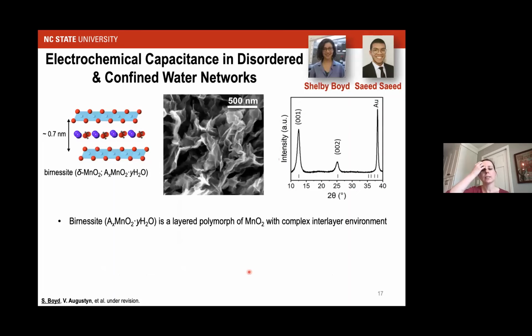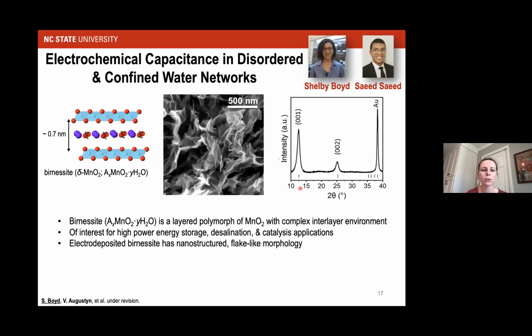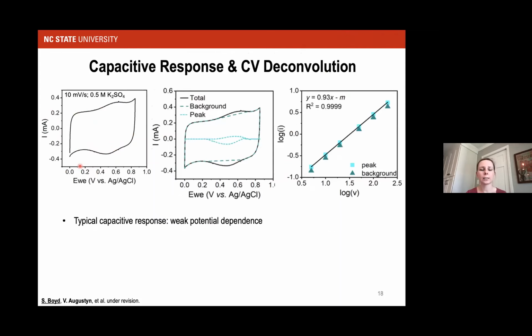To look into this in more detail, we started to work with birnessite itself, that is, birnessite that was synthesized directly. This is the structure of birnessite, very similar to what I showed before, except now all the transition metal here is just manganese. You have a single layer of water, and with that you also have some cations present. We do an electrodeposition of the material, and these are the nanoflakes shown here; we wanted a thin film morphology for the characterization tools that we were going to use. And this is the X-ray diffraction showing the layered structure. This material is of interest for high power energy storage, but also desalination, as well as catalysis applications. Interlayer spacing is about 0.7 nanometers, so fairly large, and it contains that structural water.